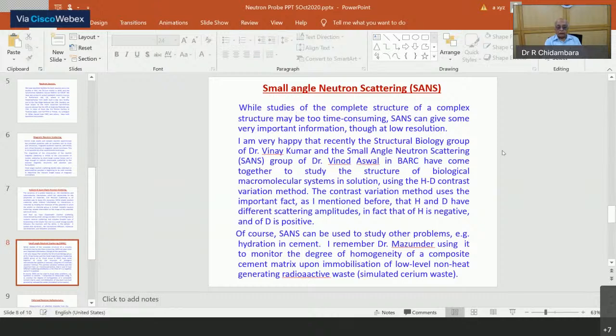And I'm very happy that recently the structural biology group of Dr. Vinay Kumar and the small angle neutron scattering group of Dr. Vinod Aswal have come together to study the structure of biological macromolecular systems. Here they use the HD contrast variation method. As I mentioned, the scattering amplitudes of H and D are different. Not only that, because of resonance effects, the scattering amplitude of H is negative and that of D is positive. In fact, for any group, you can put a suitable combination of H and D so that you can make an atom disappear, or you can totally titrate it and change the scattering amplitude. And this method can give you a very powerful technique to locate the positions of important groups in biological molecules.